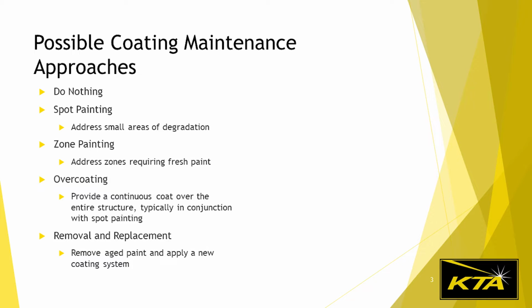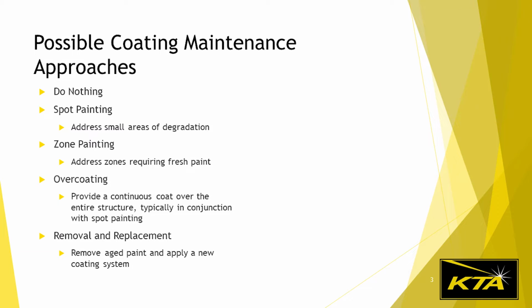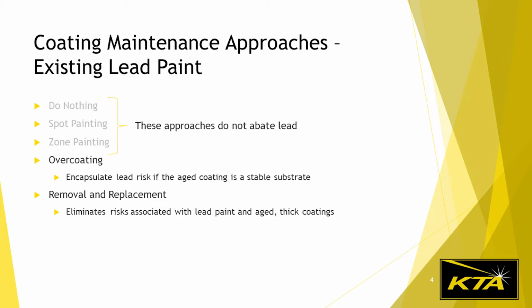Overcoating, application of a new coating over an existing coating, usually in conjunction with spot painting. The existing coating should be adhered well in relatively good condition. Finally, removal and replacement. If the structure does contain existing lead paint, do nothing, spot and zone painting do not abate lead. Overcoating can encapsulate it. If the lead risk is an aged coating in stable condition but does not remove the lead, removal and replacement will eliminate the risks associated with lead paint.